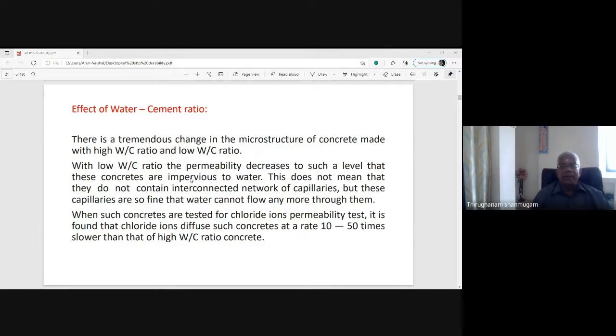With low water cement ratio, the permeability decreases to such a level that these concretes are impervious to water. This does not mean that they do not contain an interconnected network of capillaries, but these capillaries are so fine that water cannot flow through them anymore. If the flow of water through the microstructure is prevented, it means the concrete is automatically impervious to water, so the external agents will not affect the interior portion of the concrete. So there will not be any deterioration or disintegration of the concrete. So durable concrete is produced.